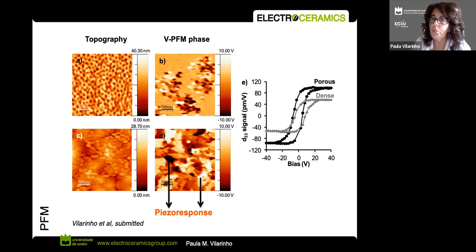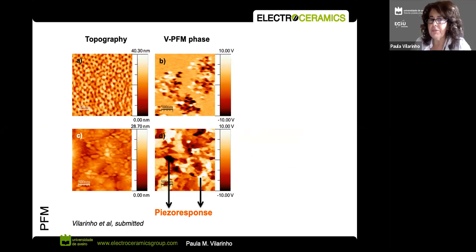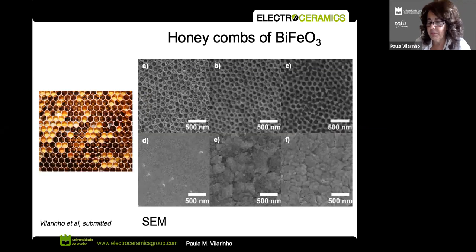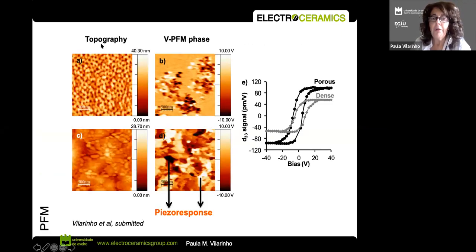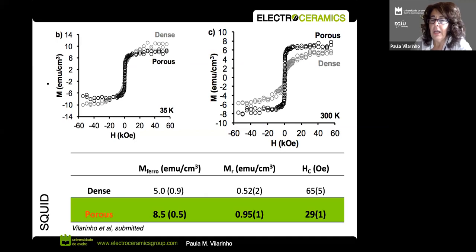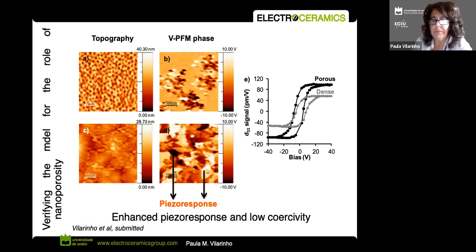The same phenomena. So to prove our theory, we used different types of materials, as I mentioned to you, lead titanate, bismuth ferrite. We observed the same phenomena. For the porous materials, we had better, easier switching because we create high electric fields around the pores that will help the dipoles to change, the domains to switch, and then just facilitate the switching polarization. And also we measured the magnetic properties, and we verified that there is also an enhancement of the magnetic response in the porous materials. So again, we prove in a different system that the nanoporosity will really improve the performance of our materials.